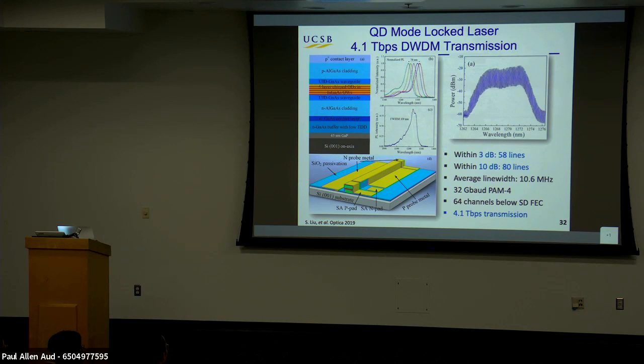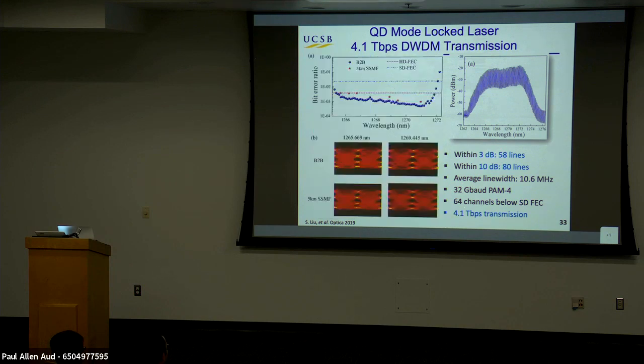And so it's just a classic colliding pulse mode-locked laser. So you've got a saturable absorber in the cavity. And this pulse with its reflection gives you passive mode locking in that device. And this is the spectrum. It's hard to see the lines at this resolution, but within 3 dB of the peak, you've got 58 lines, each at 20 gigahertz spacing. And we put 32 gigabaud PAM4 on each of those. And so then there's 64 channels that get transmitted within the FEC limit.